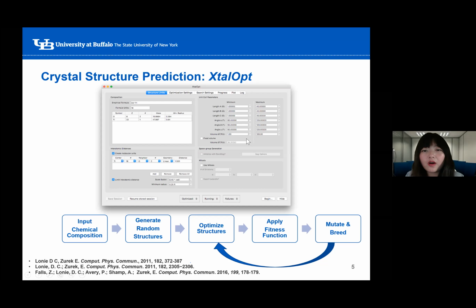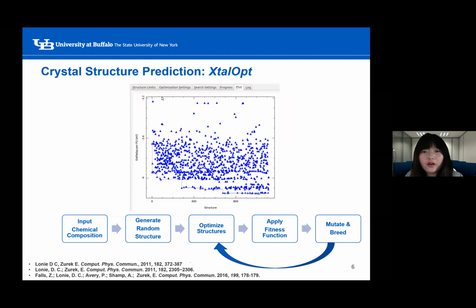The newer version of XtalOpt also allows us to input space group and define a range of formula units for each run. Then XtalOpt will generate random structures as the first generation based on the criteria we put in as input. And these structures will be optimized using density functional theory implemented in the Vienna ab initio simulation package. And after optimization, XtalOpt will apply a fitness function based on enthalpy to evaluate these structures and to select the parental structures. The offspring structures are generated by applying mutation and breeding operators on the selected parental structures, and then the whole procedure loops back to the optimization step. Ideally, we will find the global minimum structure after many generations.